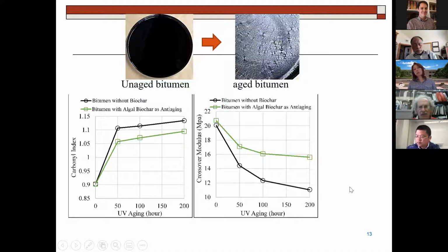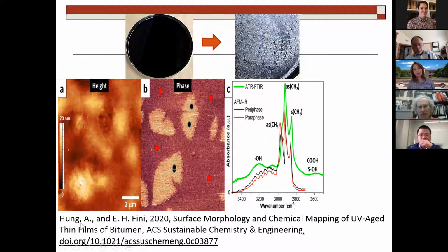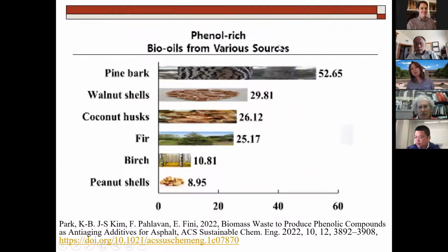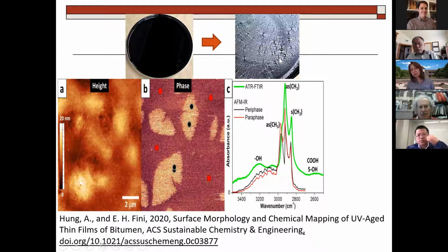What does that mean in terms of actual chemical functional groups? Here is AFM-IR. We published this paper, in case you want to check details. But look at this green and red curve here. You can see they are not the same, because the green is on the surface and the red is the total binder bulk. We all know that the surface ages differently than the bulk. So if I cut this thin layer on the top, which is aged, underneath it is not as bad. On the top it is that bad, but as I go lower and lower inside, it's not as bad. And this figure literally shows that. You can see the peaks here and here are very different between green, red and black, which shows there are variations in the depth profile of aging.